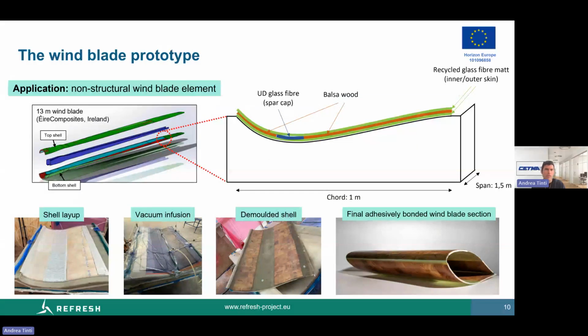Well, non-woven products can have a number of applications, but closing the loop in the wind energy sector would be the best possible result. This is why our recycled mat was used as a non-structural element in a new wind blade layup, as discussed with the Irish manufacturer EireComposites. In this picture, you can see the selected wind blade, 13 meters long, and related structure, where the inner and outer skin of both shells, now manufactured using a virgin 3-axial glass fiber, is not considered structural and could possibly be replaced by a recycled glass fiber mat.